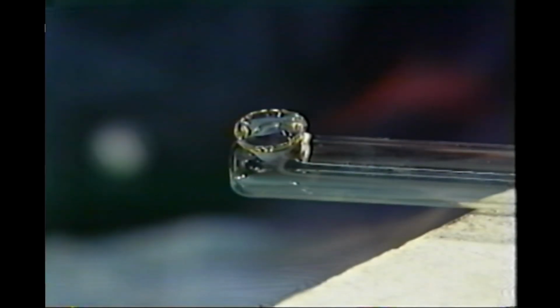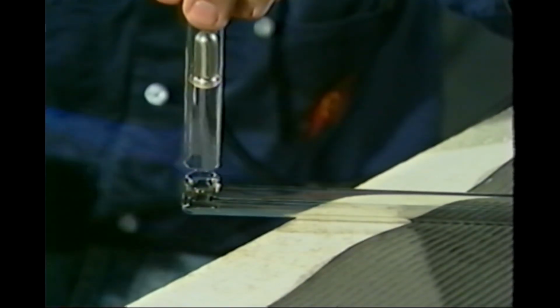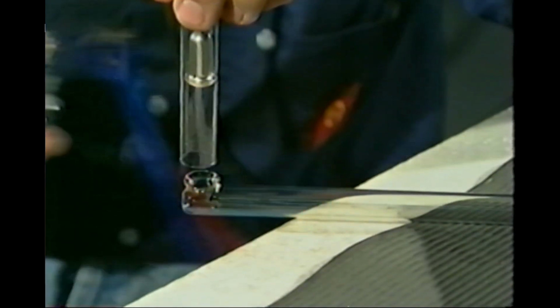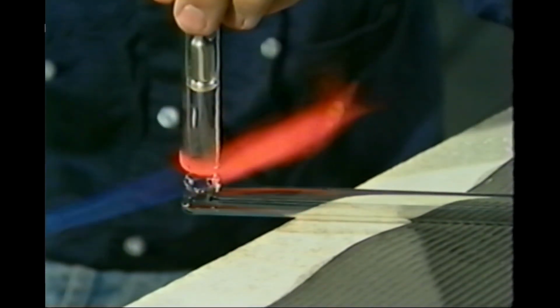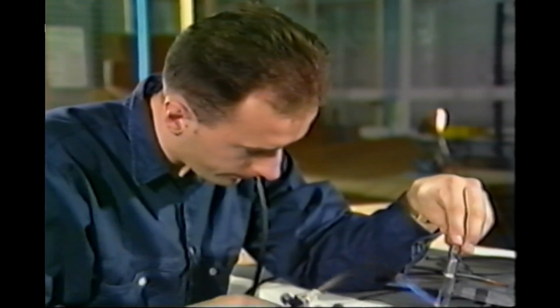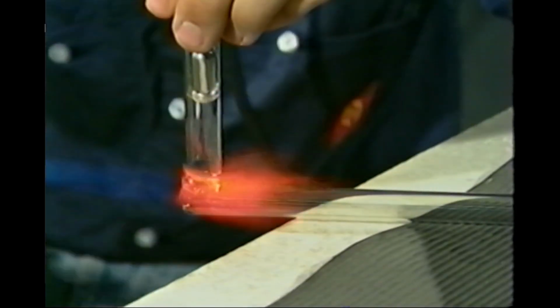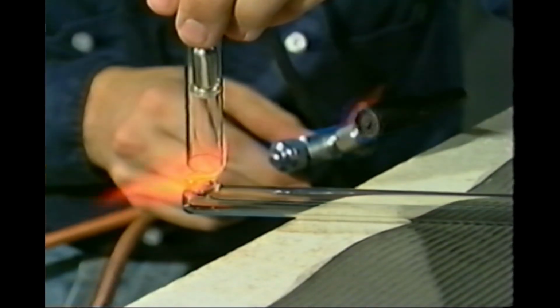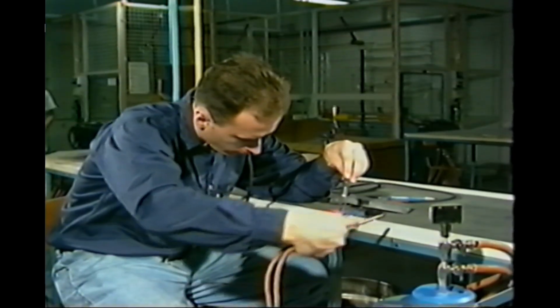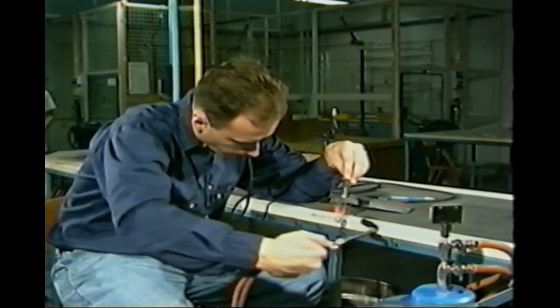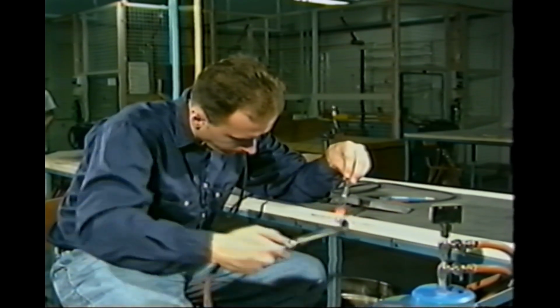Having produced the butt end and hole with a soft flame, preheat the open end of the electrode glass. Reduce the gas content of the flame to produce a wide, fairly strong flame. First, melt the open end of the electrode glass sufficiently. Bring it into position close to and directly over the electrode hole.